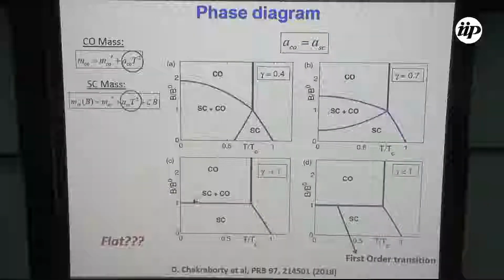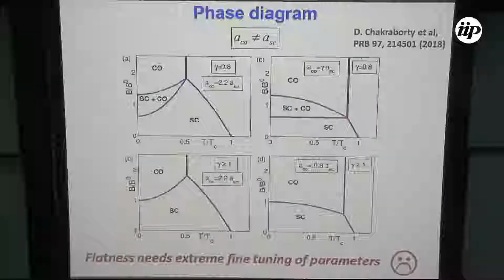To understand that, I go back to the parameterization of both masses. What we have done while plotting this, we have taken the coefficient of the temperature dependence of each of these masses to be equal. So let's see if we change it slightly. If we change it slightly, what happens? You can see that this line can be like this, it can be like this, it can be anything. So to cut the story short, we need extreme fine-tuning of parameters within a Landau-Ginzburg theory to get this flatness in the onset field. So we are not happy.